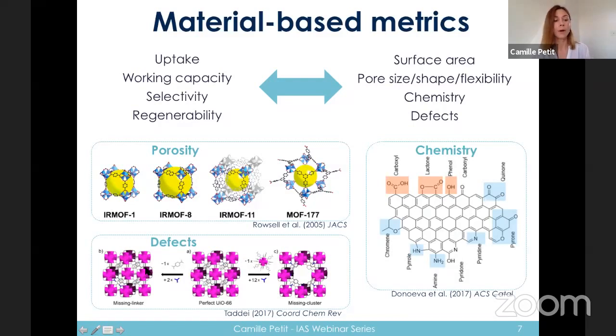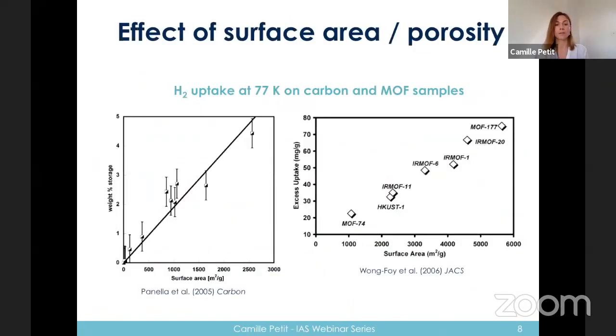So if we go into more details and look at examples of those different trends, we see here, for instance, the influence of the porosity on hydrogen uptake or hydrogen storage on carbon sample on the left and MOF sample on the right. And you see that as we increase the surface area, we increase the uptake of hydrogen, which is a common trend observed for hydrogen storage.